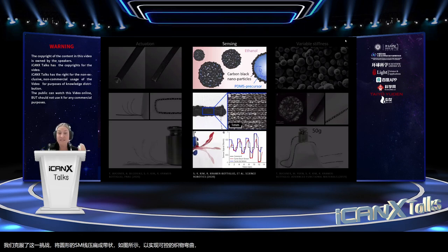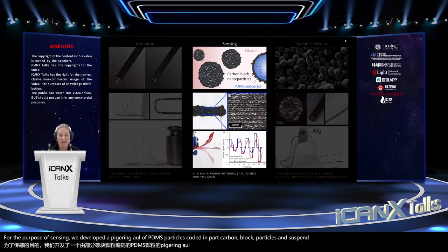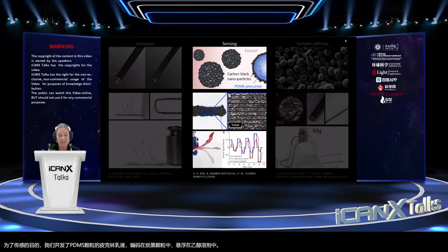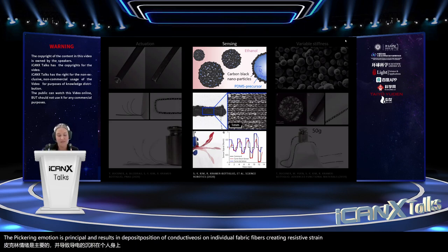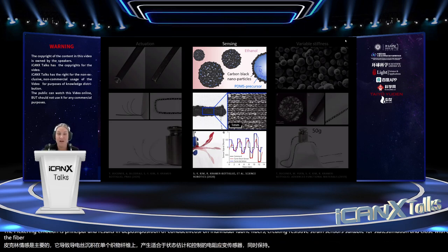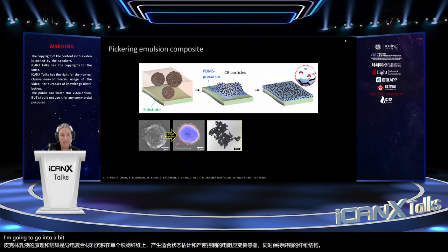For the purpose of sensing, we developed a Pickering emulsion of PDMS particles coated in carbon black particles and suspended in ethanol solvent. The Pickering emulsion is printable and results in deposition of conductive composite on individual fabric fibers, creating resistive strain sensors suitable for state estimation and closed loop control while maintaining the fiber architecture of the fabric. So I'm going to go into a bit more detail on this Pickering emulsion.